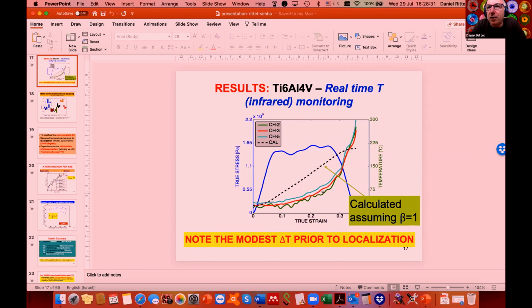As a metallurgical engineer, originally that's what I am, I know that in order to significantly soften a material, you need to reach, let's say, back of the envelope, half the melting temperature in absolute homologous temperature, T divided by Tm, roughly. Because material softening is related to diffusion in a material, and diffusion does not kick in before half Tm. So you now get the two extremes. The mathematical answer, which says any slightest perturbation can be a problem, and the engineering answer, which tells you that as long as the temperature rise is not significant, global softening is not expected to occur.